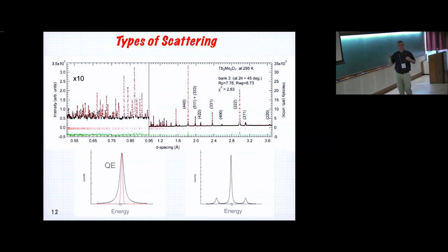You put 3 grams, 5 grams, 10 grams of material in your beam, and this is the average structure. And you refine it with the average. If you're an aficionado and you really care, you can start looking at the background down here. It's called pair distribution function analysis, or total scattering. And in this background, you'll see lots of data isn't on the fit. And that will be local disorder. And so we'll look at that a bit later on. But in diffraction terms, you get an average of the structure.